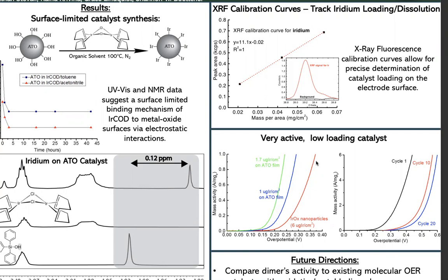We see our novel catalyst has significantly higher performance when compared to the state-of-the-art iridium oxide nanoparticles at a reduced mass loading. This is likely due to the fact that higher loading catalysts have many of their active sites covered up, decreasing the performance. We also observed catalyst segregation, seen here on the right, likely due to the iridium only attaching to the metal oxide surface via electrostatic interaction, causing them to degrade.